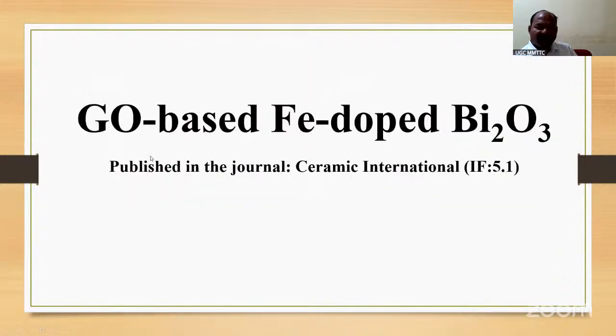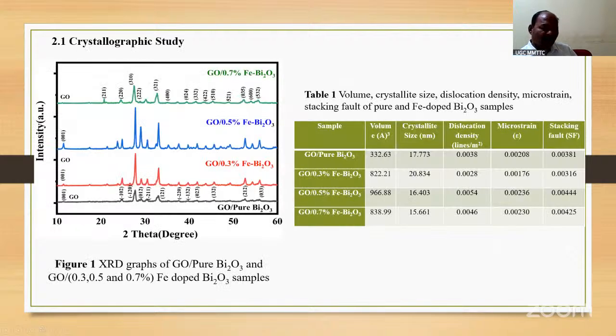Now graphene oxide based iron doped bismuth oxide is more interesting, and this paper was published in this. Then the crystallographic study, and these are the parameters which we calculated, also percentage wise, and we calculated the volume, crystallite size, dislocation density, microstrain, all these. And here is the change.